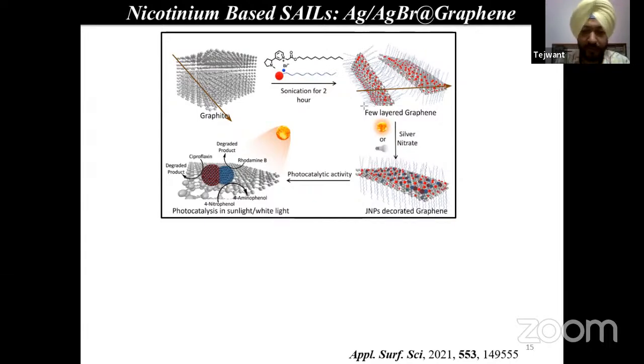We have in the aqueous solution few layered graphene appended with the nicotinium based ionic liquid which we have earlier used for the preparation of silver sulfide nanoparticles. So in this aqueous solution, we have added the silver nitrate and irradiated the solution under sunlight to obtain Janus nanoparticles decorated graphene, which we have exploited for the photocatalytic activity, not only for the photoreduction of rhodamine B but also for the photoreduction of an antibiotic ciprofloxacin as well as reduction of 4-nitrophenol to 4-aminophenol.